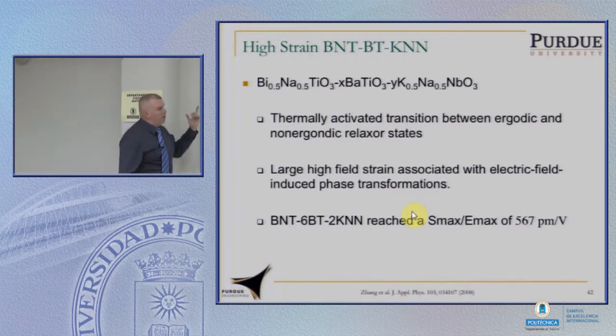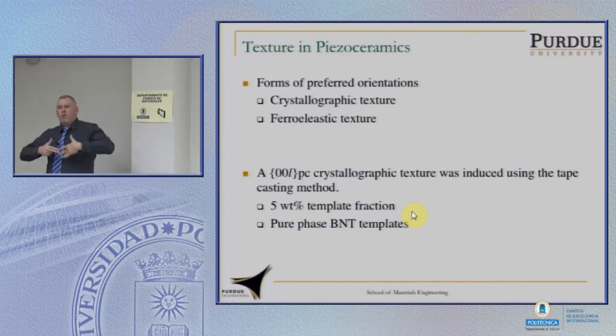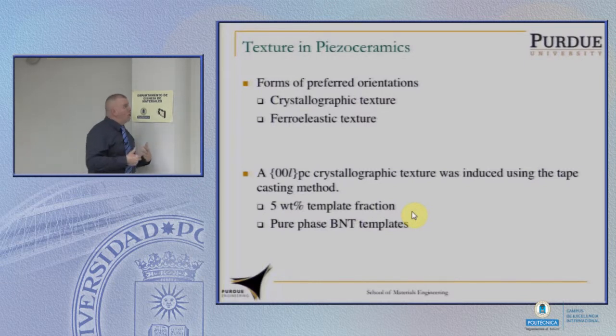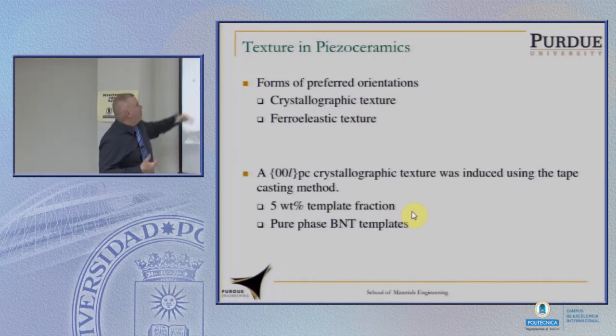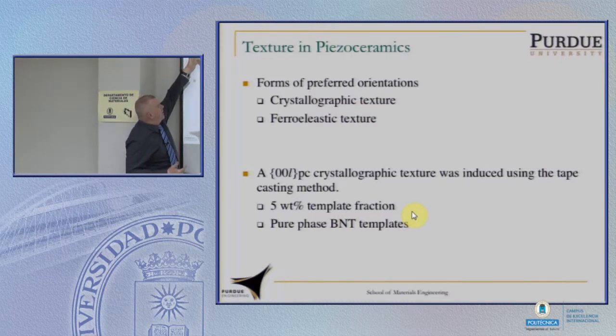What we did is we introduced these materials and we actually processed them so there was a preferred orientation. So even if they were cubic, we processed them at high temperatures so that there was a preferred orientation. So we were trying to make a material that had a preferred orientation to begin with to exploit what happens. So there we're actually looking at a crystallographic texture on top of a ferroelastic texture.